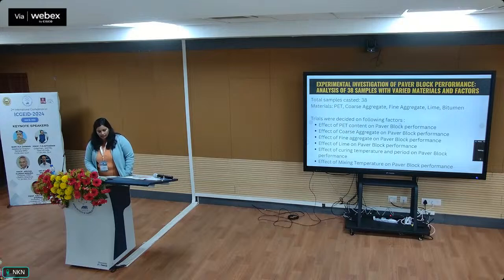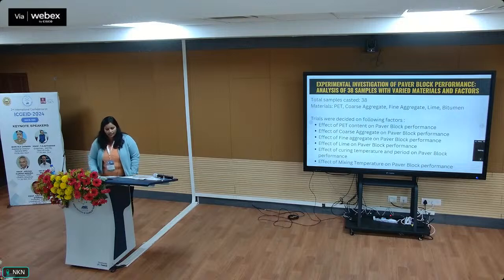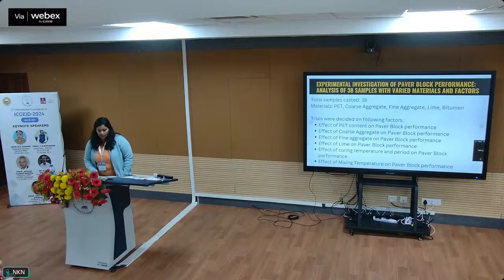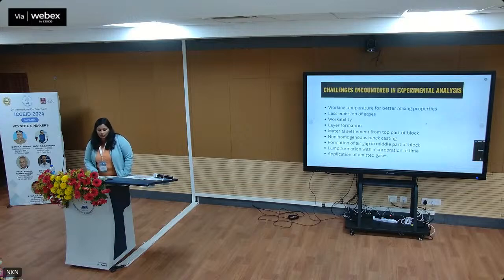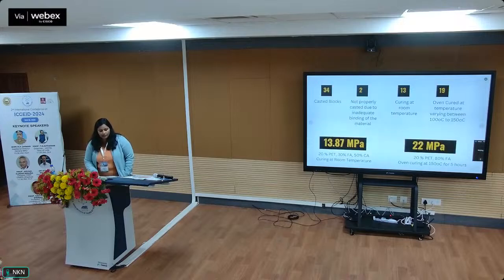These factors were extracted after the literature survey, which says that we can vary the temperature at which the plastic binder is being mixed, the percentage of the fine aggregate, and the percentage of the coarse aggregates. So we have taken these factors: what will be the effect of PET content on the paver block, what will be the effect of the percentage of coarse aggregate, what will be the effect of fine aggregate, if required what will be the effect of lime, what will be the effect of curing temperature, and this played a very major role in our study, and what will be the effect of mixing temperature on paver block performance.